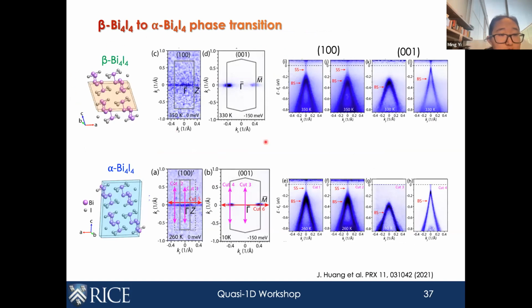So I've already shown you what we see from the beta phase here. This is from the topologically dark 001 surface. These are the pair of Dirac crossings from the 100 surface within the bulk gap. Now, when we go to the alpha phase, if you zoom out from very far away, you hardly see any difference between the two, except perhaps if you know where to look, you can see the band doubling effect as seen here, for example. But the feature is actually quite subtle.